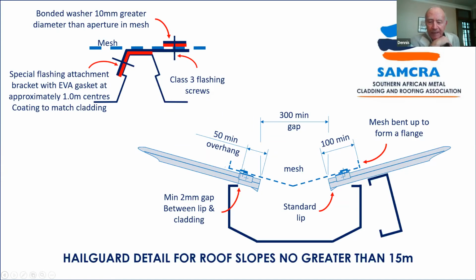Please note that with that sort of gutter and that type of Hailguard that is positively fixed to both sets of sheeting, you can't have sheet lengths in excess of 15 meters. Otherwise, thermal movement will cause that thing to flex, and it'll crack. You'll develop what we call a fatigue crack within the metal of your mesh, assuming, of course, you're using a metal mesh.